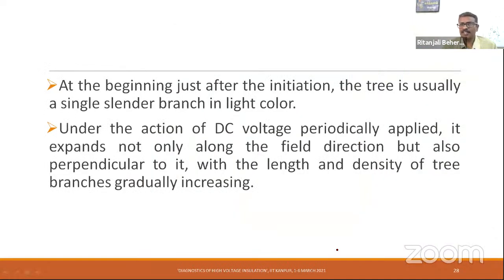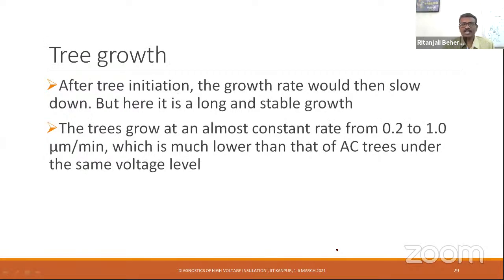So at the beginning, just after initiation, the tree is usually a single slender branch in light color. Under the action of DC voltage, which is periodically applied, it expands not only along the field direction, but also perpendicular to it, with the length and density of the tree branch gradually increasing. After the tree initiation, the growth rate would normally slow down in the case of AC. But here in the case of DC, there is a stable growth observed by the researchers. Actually, it is growing at the rate of about 0.2 to 1 micrometer per minute.